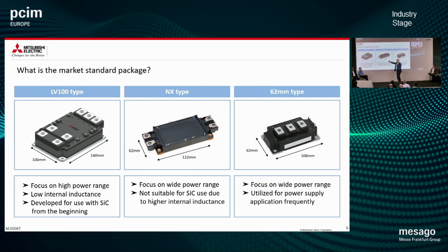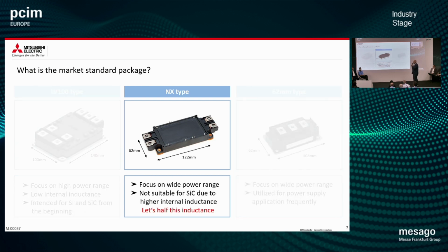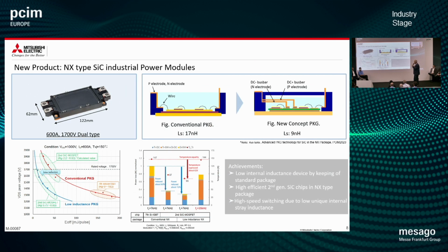But who is the Sorgenkind here? It is for sure the NX package, which is not prepared for silicon carbide and has quite a big internal inductance. How to proceed is presented on the next slide. Actually, for the conventional NX package, what Mitsubishi did was to provide a laminated busbar inside the module. It means DC plus and minus go inside the module and allow compensation of magnetic flux. The result is 9 nanohenry between P and N, versus the original package's 17, so approximately half of this inductance, and now we are ready for silicon carbide.